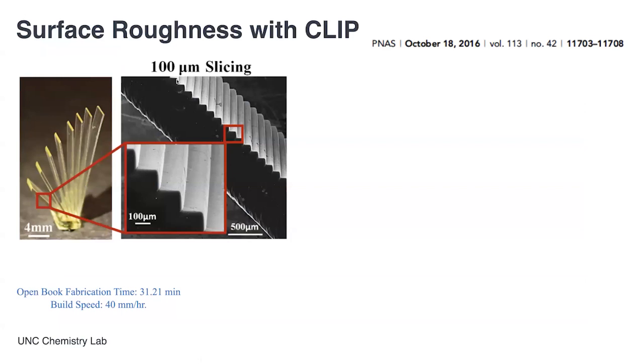But if you look at these processes, making a test pattern, I love this little study we published. If you're making this test pattern continuously, you can decide to slice this image in an STL model, and you can slice it every 100 microns, right? But if you're making this continuously and you've got 100 micron slices of images, that means the image is constant for 100 microns in Z. And then as soon as you reach that point, you change the image, and then you hold that image constant for another 100 microns in Z, and then you change it again, and you change it again.